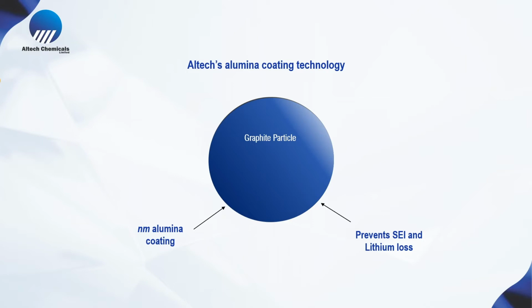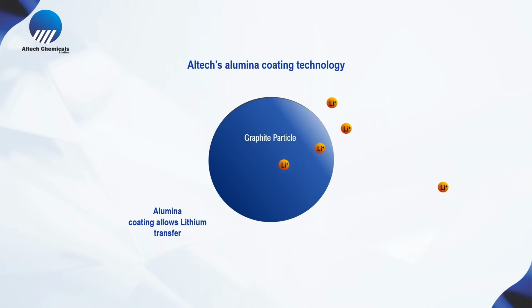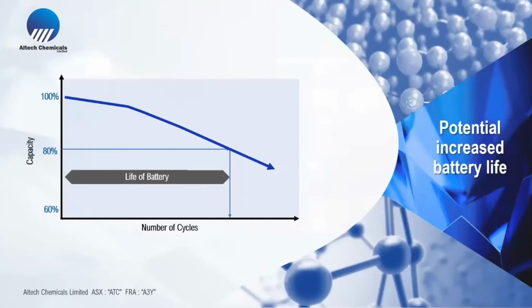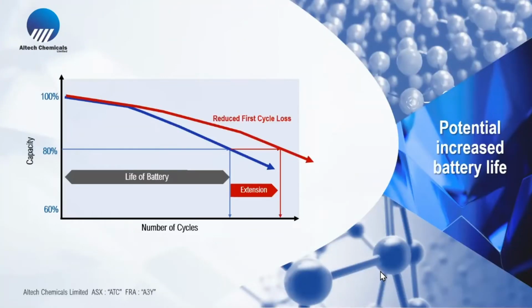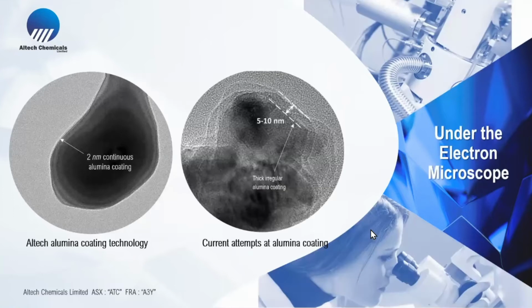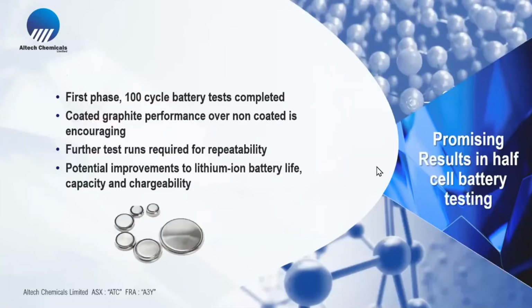We also find that any other hydrofluoric corrosive material is absorbed by the alumina layer, and it also helps with the lithium degradation. What it does is, when we coat the graphite, this is what we are aiming to have: a reduced first cycle loss, which is an extension of the battery life. We've done this in the laboratory. On the left-hand side is a graphite particle with our alumina coating. You can see the very thin continuous layer of alumina at about 2 nanometers thin. We've taken it to the battery test now, a coin battery test, and it shows very positive performance in the battery.